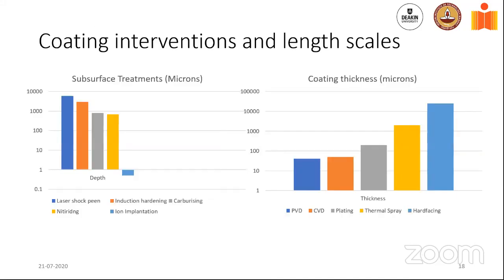And in this whole world of surface engineering, I'm going to go back and connect this to the table that we had before that showed different wear modes for different industries with different coating processes. We can essentially do two things. One is take a component surface and go underneath and change the structure and composition, which is what we do through ion implantation, carburising, nitriding, and induction hardening. Or I can take a component and essentially deposit stuff on the surface.